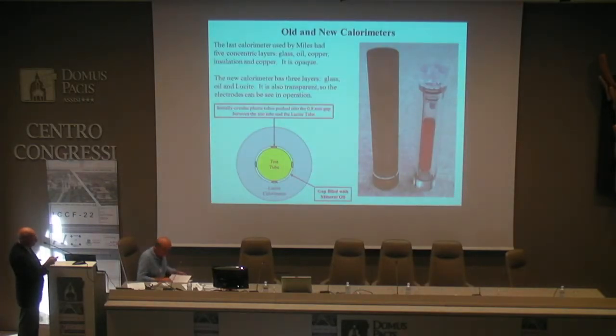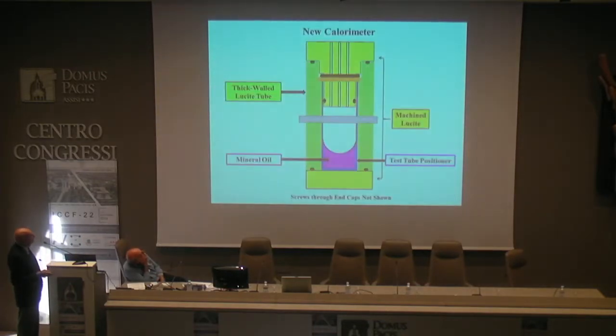The old calorimeter used by Mel Miles is shown here. It's the Pyrex test tube, and then oil, then copper, then insulation, then copper. It's too complex. I couldn't see through it, so we built a transparent calorimeter that has only 3 components: the lucite thermal barrier, a thin 800 micron layer of oil, and then the test tube in the middle. And that's working quite nicely.